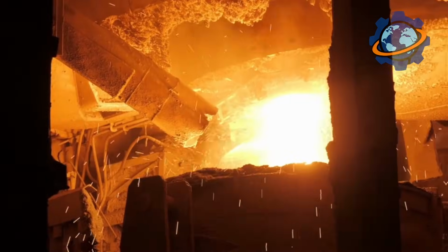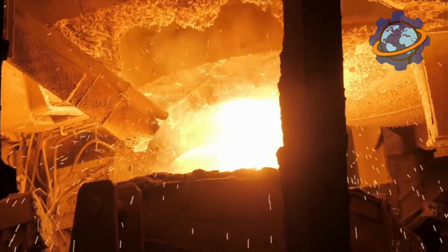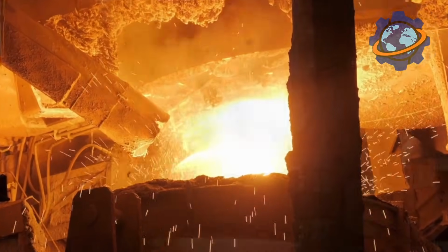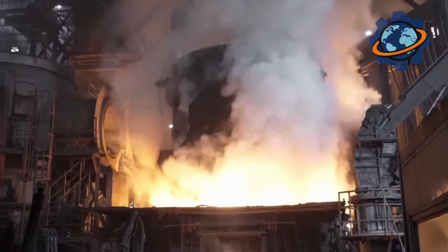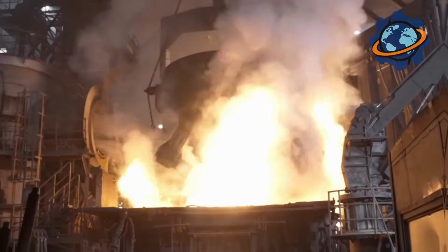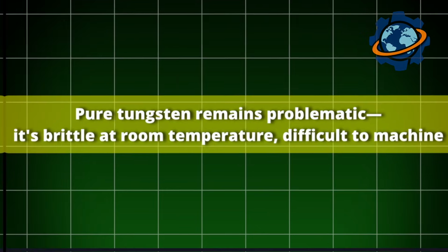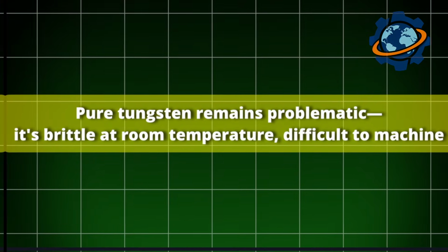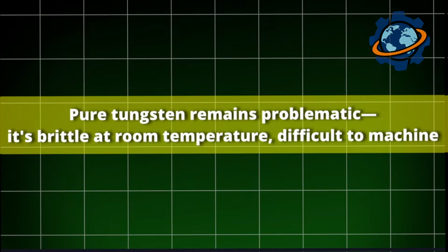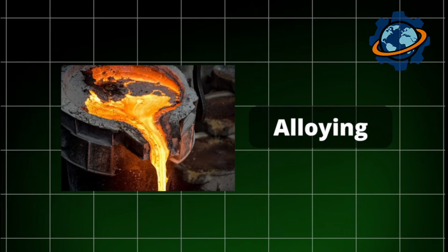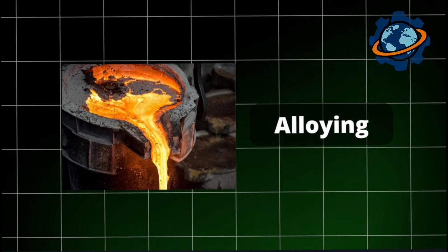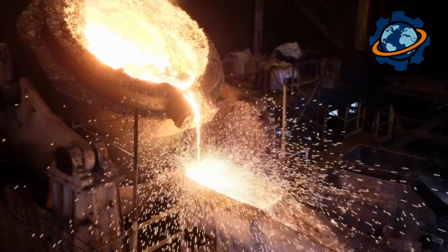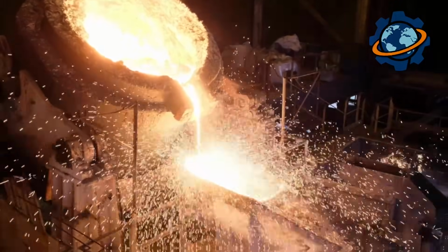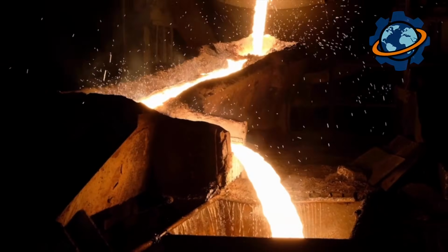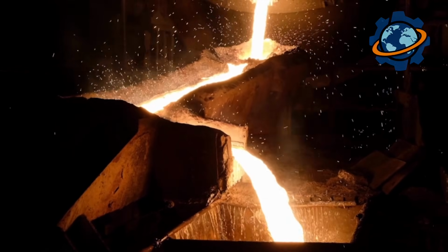Dimensional changes are predictable but significant. Parts shrink 18% during sintering. Engineers must design oversized greens compensating for this shrinkage. Pure tungsten remains problematic. It's brittle at room temperature, difficult to machine. The solution? Alloying. Adding 2% thorium or lanthanum dramatically improves workability. These elements prevent grain growth during sintering, creating fine-grained structure that machines more easily.